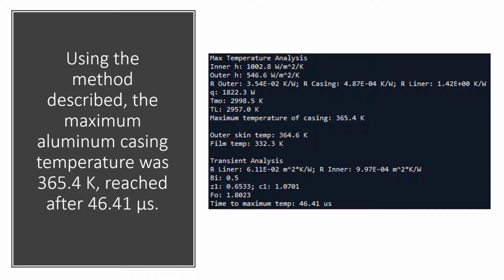The film temperature, as seen at 332.3 Kelvin, was iterated on to find the exterior heat transfer coefficient. The second section displays the resistances for transient analysis, Biot number, zeta 1, C1, and Fourier numbers. The Biot number was greater than 0.1, indicating that a first-term solution would be necessary. The Fourier number was greater than 0.2, indicating that a first-term solution would be a good approximation.